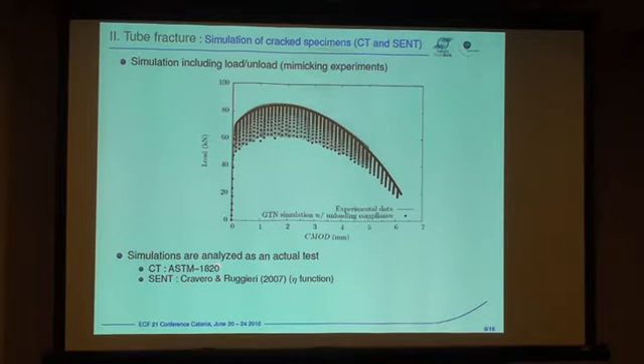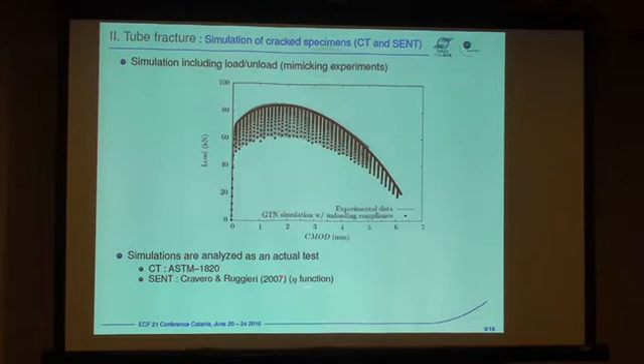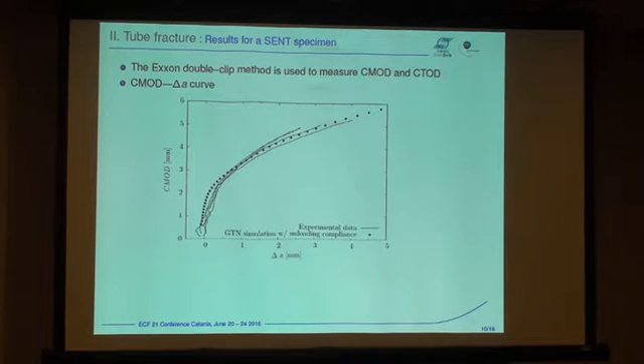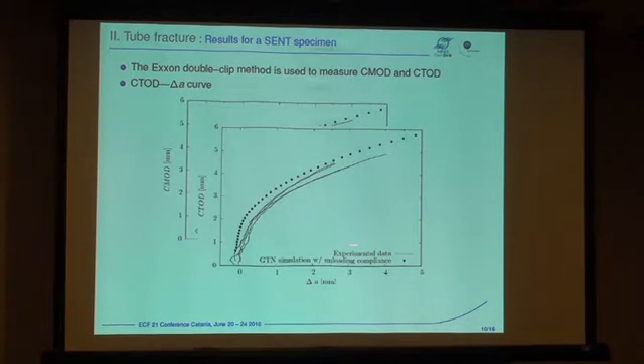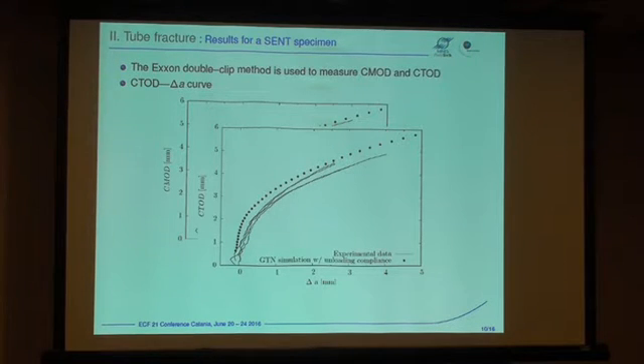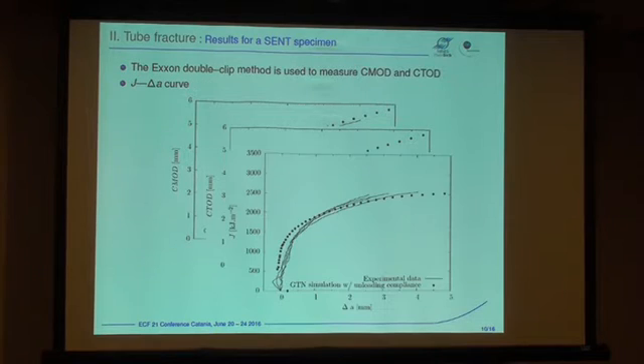For the CT specimens, we use the ASTM standard to make the calculation of the J-integral. We use the eta function from the relevant paper, which is needed to compute the J value. If you do that, you can get a very good representation of the CMOD delta-a curve and the crack tip opening displacement delta-a curve. You can see that the values of CMOD and CTOD are very low — that means the crack is really opening in a flat manner, the angle is very low, because the material is so ductile. And ultimately you get the J delta-a curve. Basically, if you get the proper CMOD–force curve, you will get these curves correct.